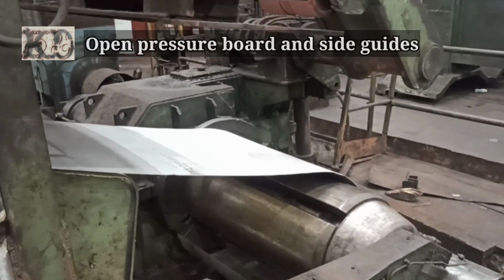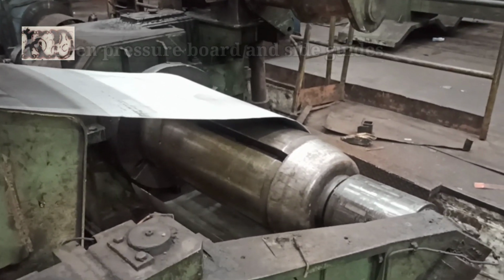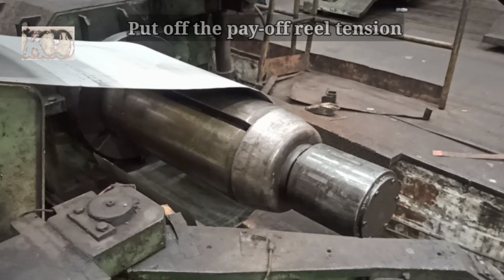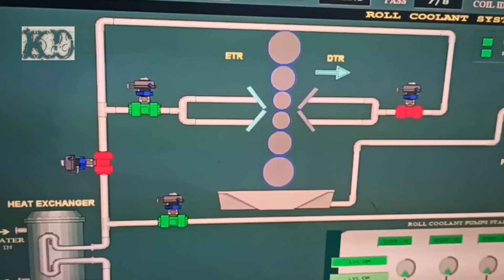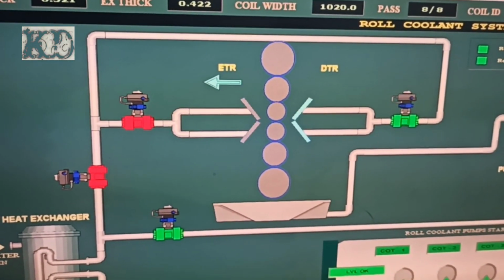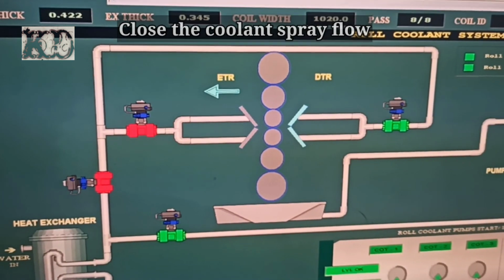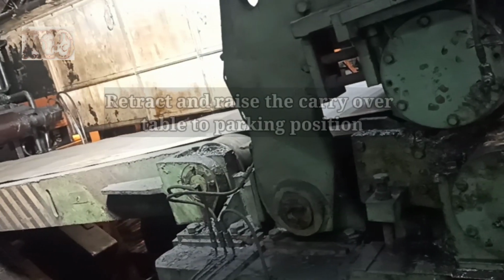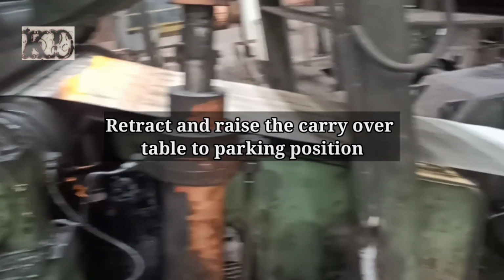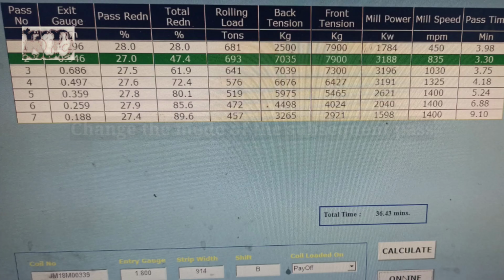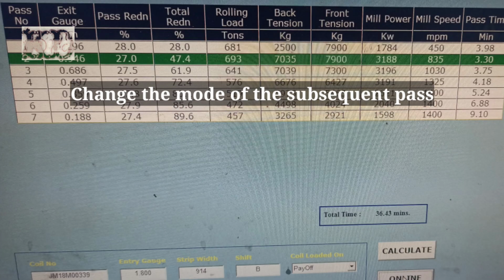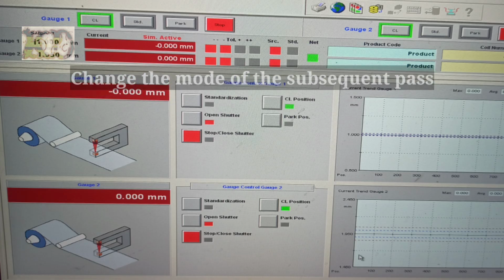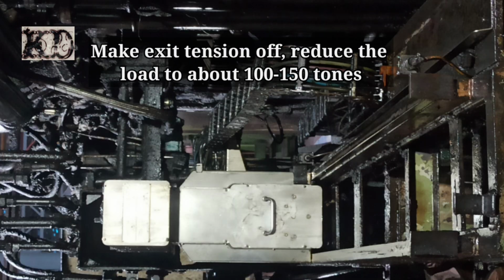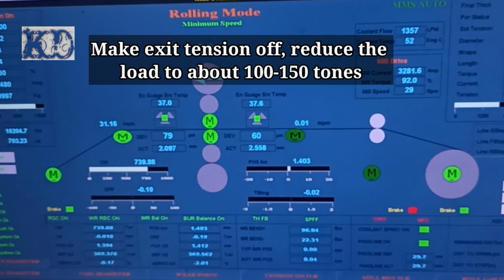Open the pressure board and the side guides. Put off the payoff reel tension. Close the coolant spray flow. Retract and raise the carryover table to the parking position. Change the mode for the subsequent pass. Make exit tension off. Reduce the load to about 100 to 150 tons.